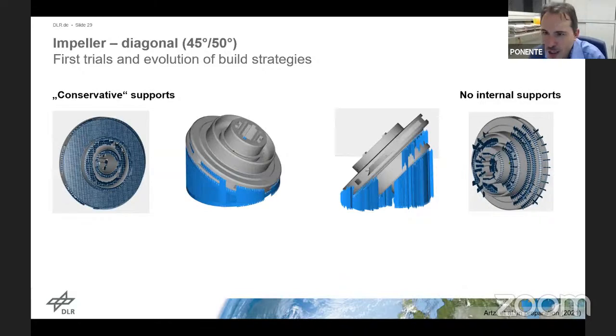So we started with the diagonal orientation. We started developing support strategies. On the left-hand side, there is an example of one orientation with very massive supports. Essentially, we could have printed a massive titanium bulk below this impeller that wouldn't have been much different. On the right-hand side, one of the early tries with a minimal amount of supports, a slightly different orientation of the impeller, but you see it's a lot less.